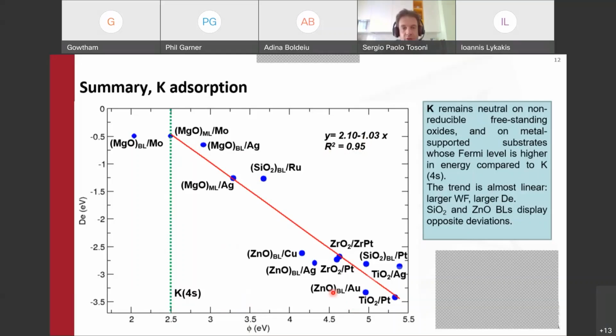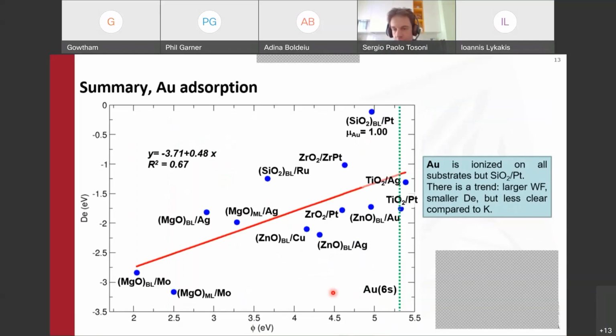What happens if we consider a species which is prone to form anions? We get the opposite trend. The smaller the work function, the larger the adsorption energy. Why? Because small work function means shallow donor states. It is easier to transfer an electron via tunneling through the film to the gold adsorbate.